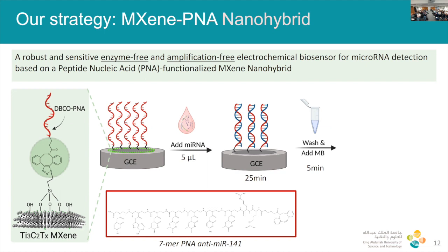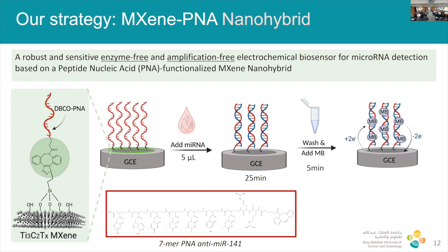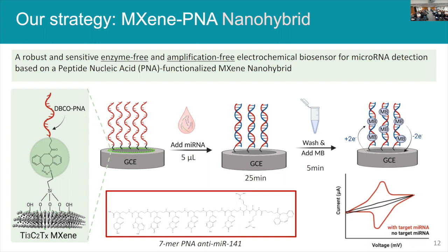The nucleic acid itself is not redox active, we can't see it, so we added a reporter called methylene blue, very commonly used to detect the presence of duplexes. The methylene blue will intercalate between the PNA-microRNA duplex, and what we're actually detecting as our analytical signal is the oxidation-reduction of this methylene blue, and electron transport is mediated through the pi stack, through the duplex down to the electrode, and that's what we detect. In the presence of microRNA, you see the red curve, you see an oxidation peak current detected there. Without any microRNA or with non-specific microRNA, you don't see anything. You see a flat curve as you're sweeping your voltage. You don't see any current there.